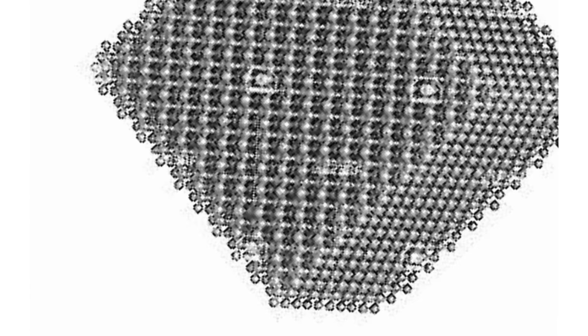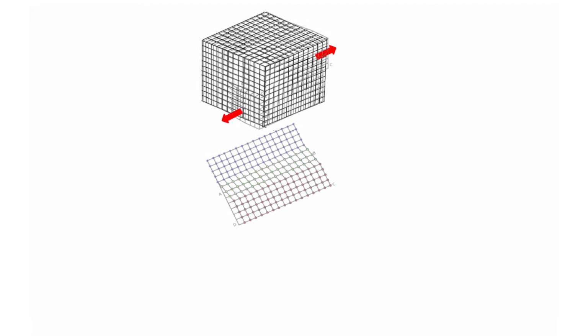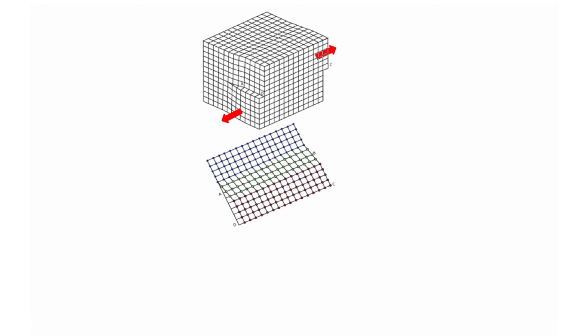To show the principle of the creation of a dislocation, an atomic model of a 3D lattice is shown here, and you can see again, a simplified version. It's a cube with lattice planes, and if we pull the top half against the bottom half, so we shear it, in opposite directions, then we see a slip edge, which is introduced into the material. And if we draw a line along the start of this slip edge, which goes across the crystal, then we can see this is a dislocation.